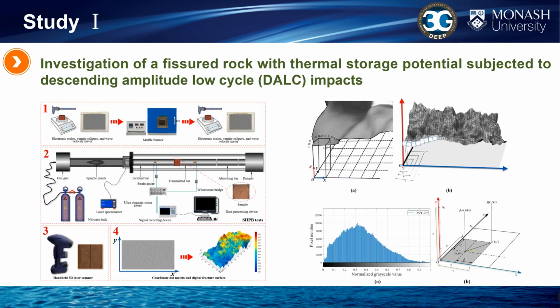In Study 1, we conducted an investigation of a fissured red sandstone with thermal storage potential subjected to descending amplitude low cycle impacts. DALC impact tests are conducted on the fissured red sandstone after thermal treatment utilizing a modified split Hopkinson pressure bar, and the point cloud data of the fracture surfaces from the failed specimens are captured using a high-precision 3D laser.